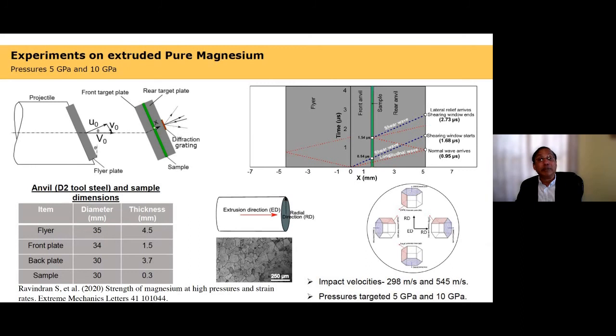As you know, magnesium is a lower strength material. And so here, once again, the shearing window is about 1 microsecond. We are compressing along the extrusion direction along the a-axis, and then we are shearing along the rolling radial direction. Here we only look at low pressures of 5 and 10 GPa. The grain size is about 70 microns.